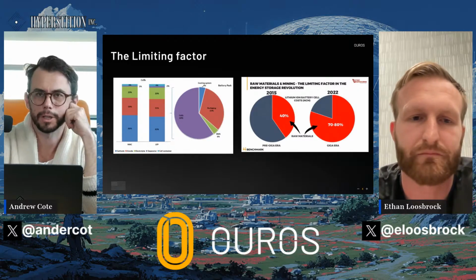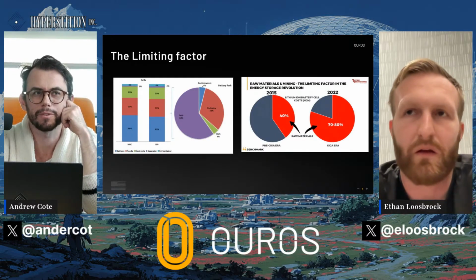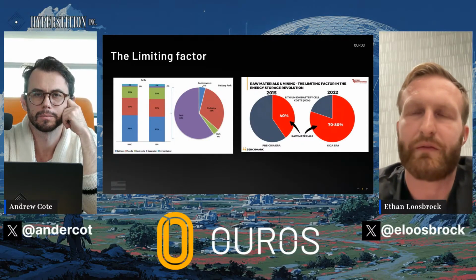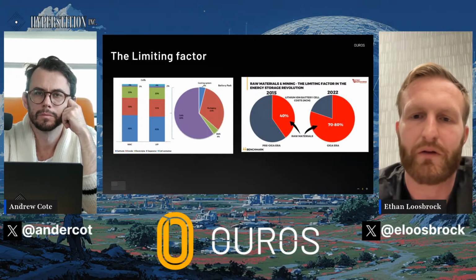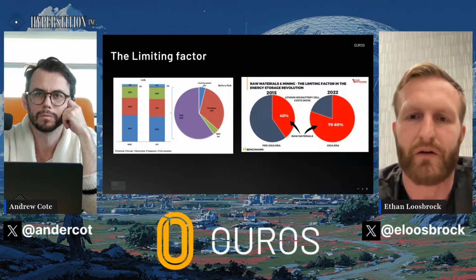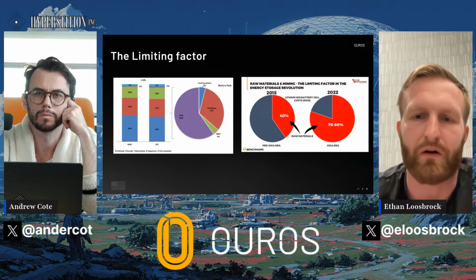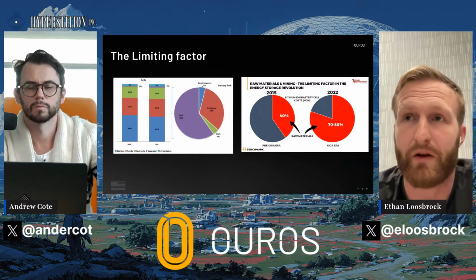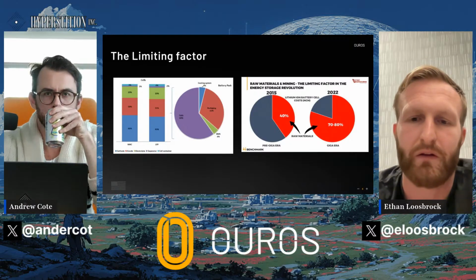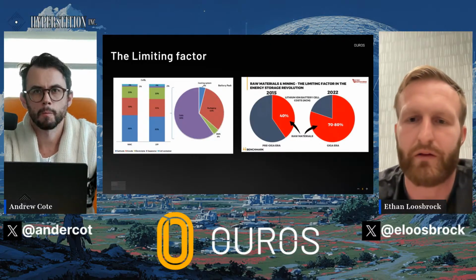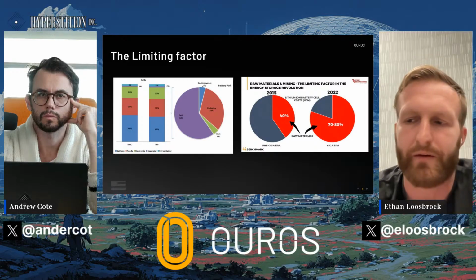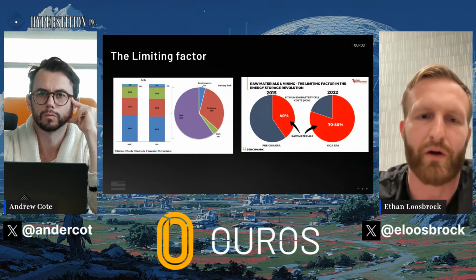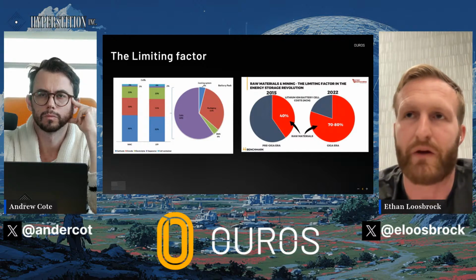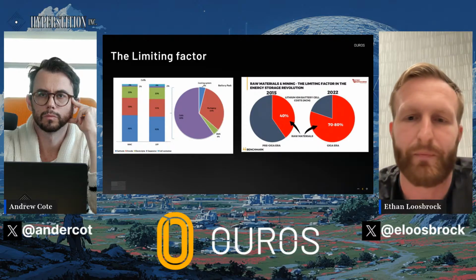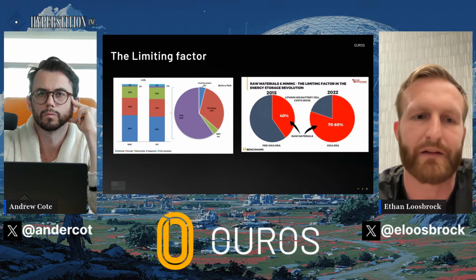Tesla is fully vertically integrated in their whole battery stack, right? They now have their own lithium refinery and everything. Yes. I don't think they're mining the lithium. There are two types of mining: brine and hard rock. Brine comes from these salars in South America primarily. There's one in California actually too, but the salars have various alkali metal chlorides: sodium chloride, lithium chloride, potassium chloride. They take these chlorides and put them in evaporation ponds, and they drop out one chemical at a time. They drop out the lithium in one pond, and the sodium in another pond. Then you end up with a lithium chloride that you need to turn into either lithium hydroxide or lithium carbonate. And that's what goes into the cathode.